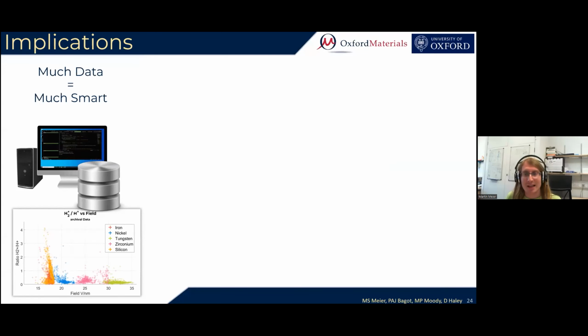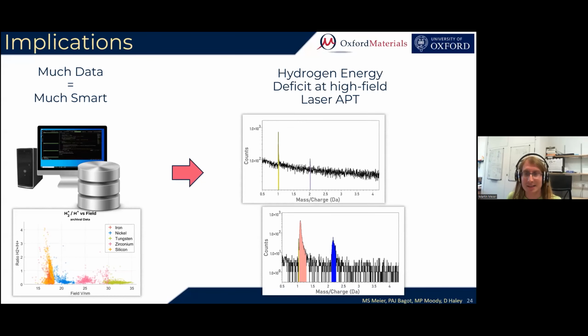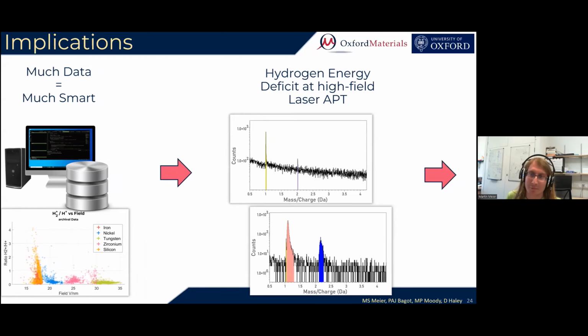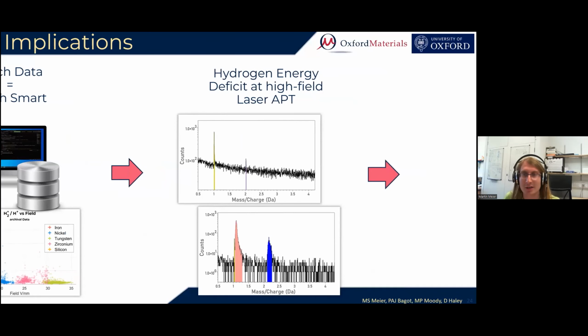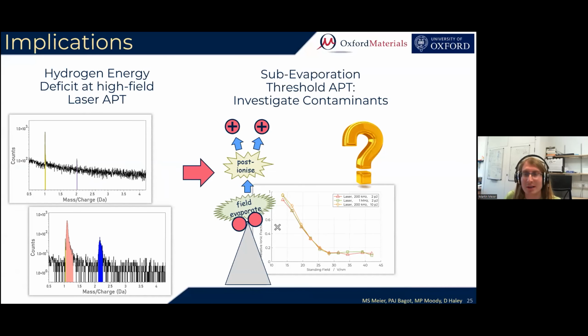Now, before we go to the grand finale, a quick recap of what we have just seen. If we have a big pile of past experiments, then you have something that's extremely useful, because when there are observations that we can make statistically across many APT experiments, they will be in there and we can dig them up. What we do is we focus on contaminant hydrogen, and we find that indeed there is something interesting and it appears to happen in laser mode at high electric fields. So this is leading us to our experiments where we run these tungsten tips, and we find, yeah, there is something, and it seems to involve an energy deficit. On top of these experiments, we can then stack these runs below the evaporation threshold. And they give us a very clear image of which parameters are influencing the hydrogen behavior and how, and we can then start speculating what might actually happen on a molecular level on this tip.